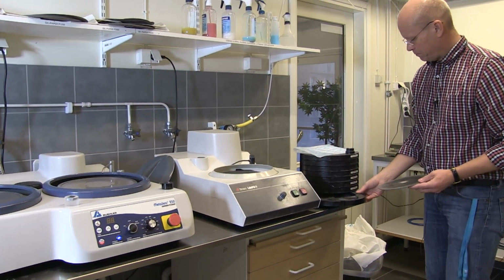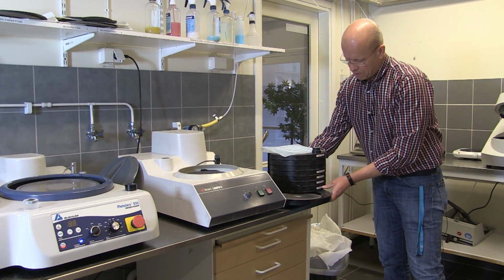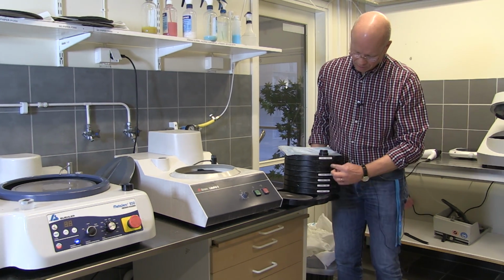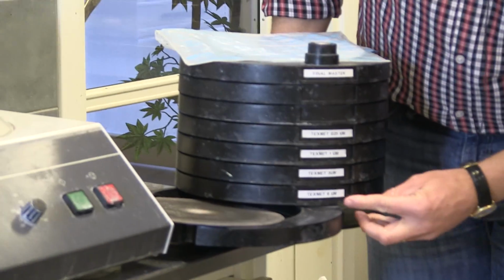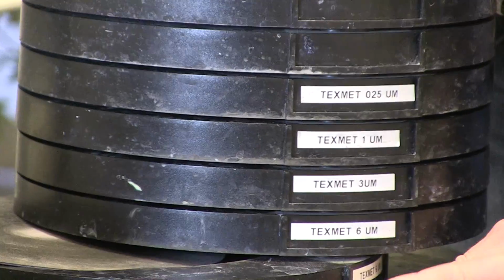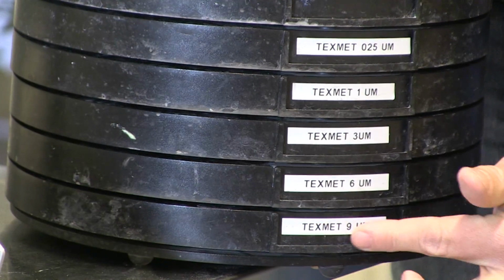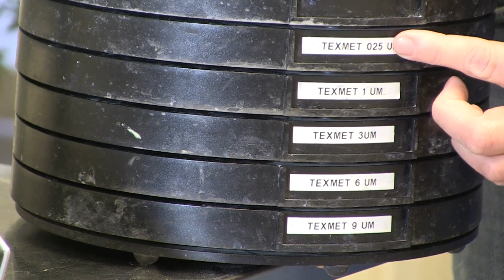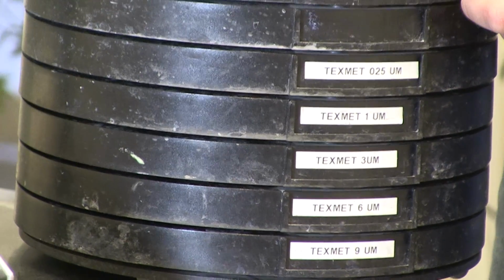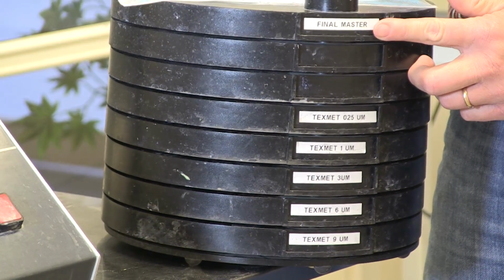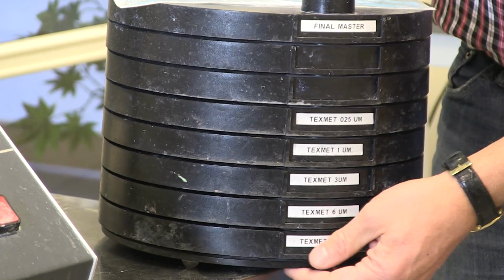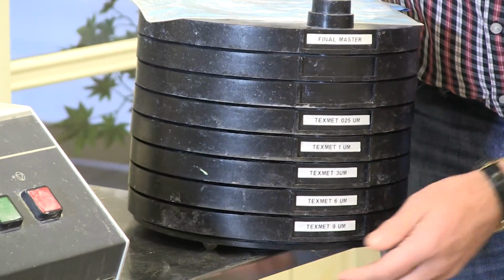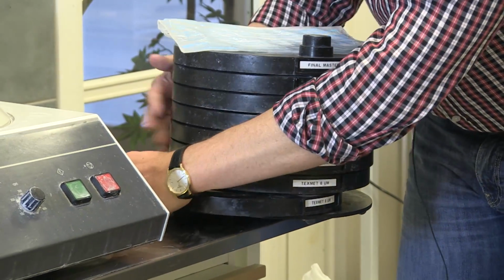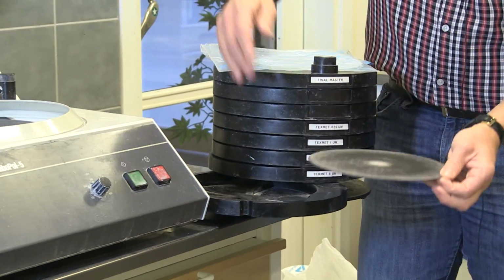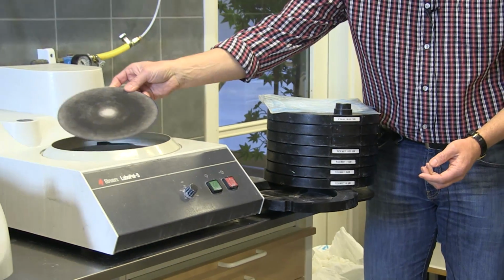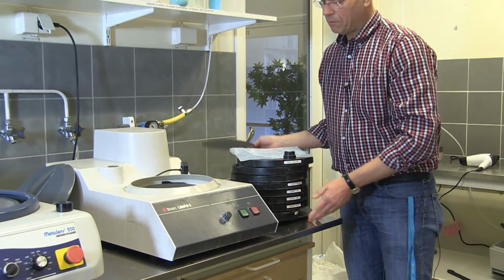By the way, these cloths are stored in this holder here. And here it's marked with 9 micron for the one that I will use now. And we have 6, 3, 1, quarter of a micron diamonds, and then we have a top one here for final polishing. I will talk more about final polishing later on. It's only one size of diamonds on each cloth, so because of that we have separate ones. Put it into the machine.